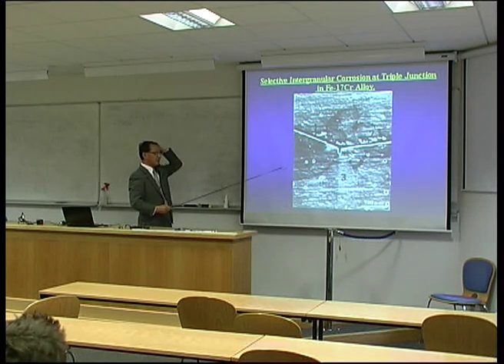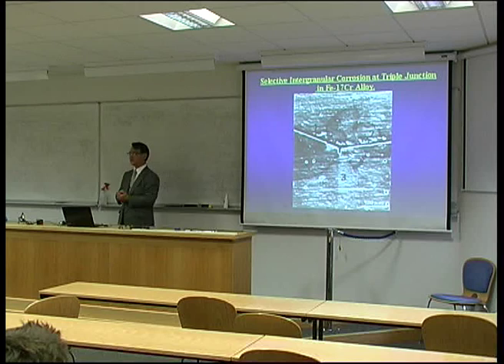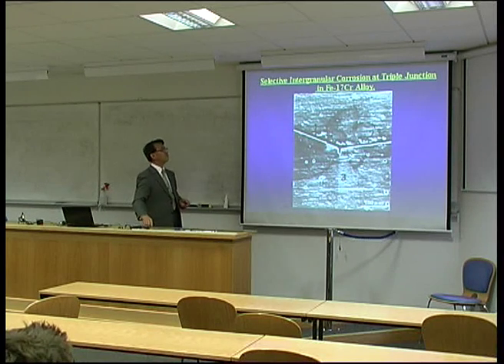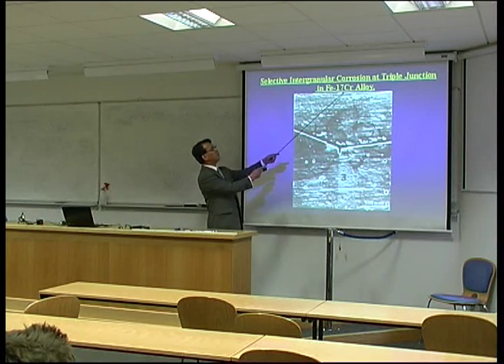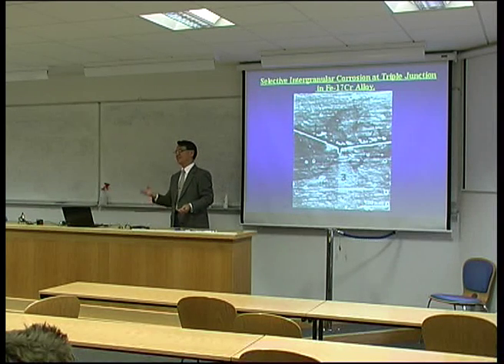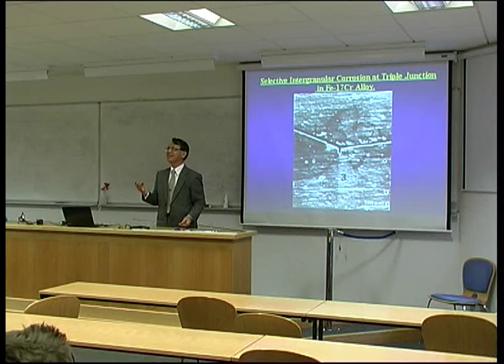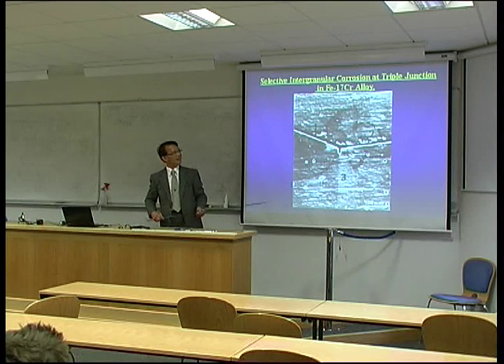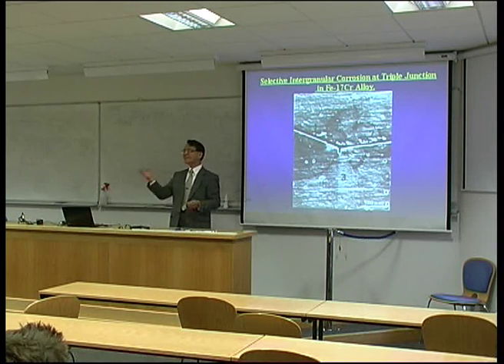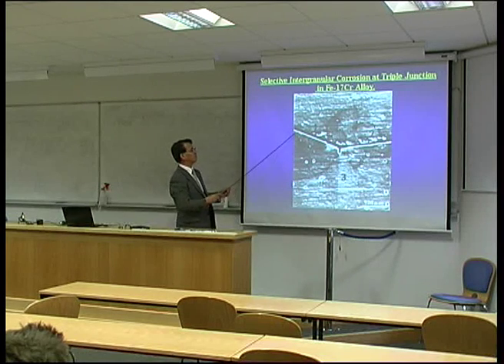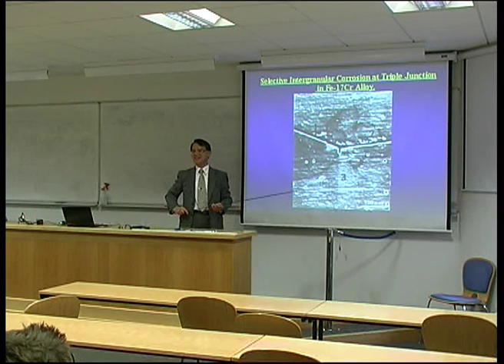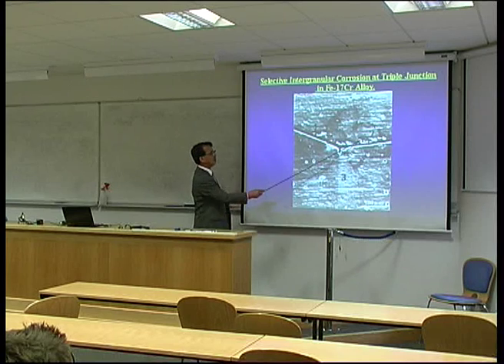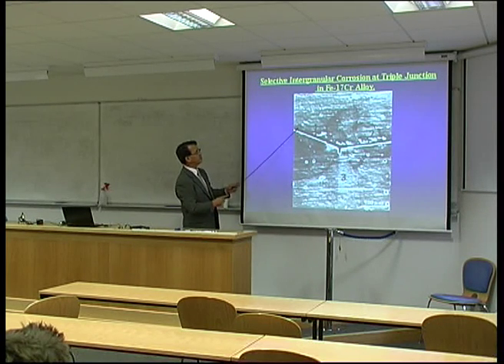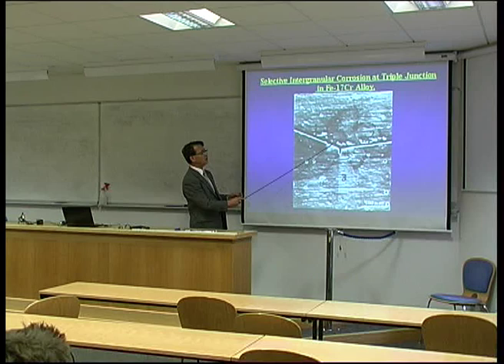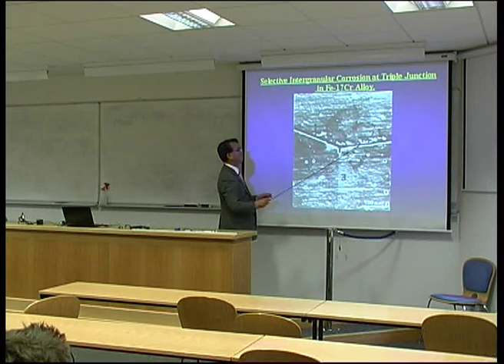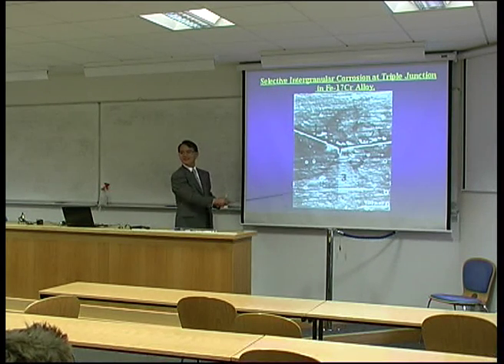Anyway, this is one of the simple demonstrations. If you take an iron chromium alloy, just the ferritic stainless steel composition, and corrode it in the acid solution, grain boundaries are corroded like this, but not all boundaries are similarly corroded. This is the boundary that was heavily corroded. This is the secondary, heavily corroded. This is very resistant to corrosion.